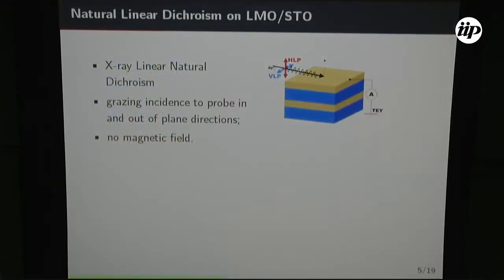Then we did the dichroism. Okay, the first approach was to do linear dichroism. Here I'm representing more or less this experimental setup. So we use a grazing incidence on the sample. In real life, this is tilted. I represent it here just to make it easier to relate with the results. But in our case, the samples always end with a top 2-unit cell strontium titanate, and then the manganite thickness is changed for several samples.